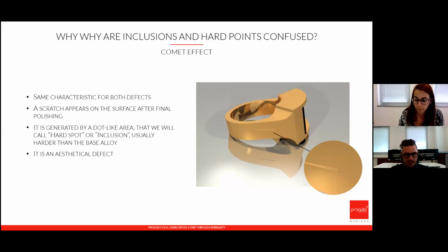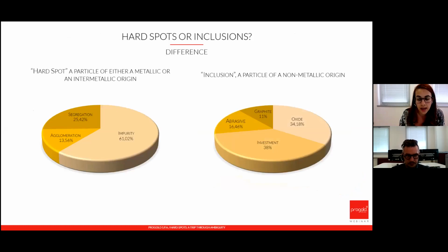So what's the difference between an inclusion and a hard spot? A hard spot has a metallic origin, and can either be a metallic element or an intermetallic compound, while an inclusion is usually of non-metallic origin. In particular, it's very common to have a ceramic origin in this case. We can also divide these two defects into very big categories. In the case of hard spots, we have three macro categories: impurities, agglomeration, and segregation. While for inclusions, we have four macro categories, which are investment, oxide, graphite, and abrasive.